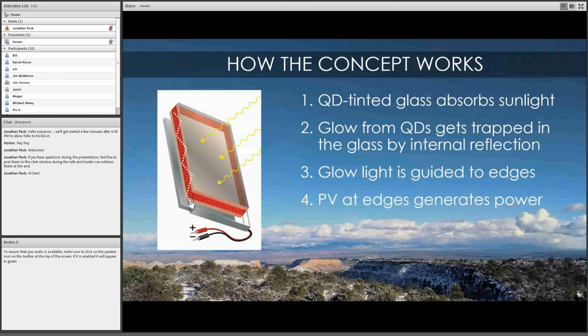We can do a coating on a sheet of glass, but more commonly, we make a laminate structure where our material is in a polymer in between two sheets of glass. There's different approaches to making a luminescent solar concentrator, which is what this is called, but we do it as a laminated sheet of glass with quantum dots in the inner layer. But anyway, the quantum dots absorb sunlight partially, and then they are glowing. That's what quantum dots do. They're very effective at absorbing and then re-emitting that energy as luminescence.